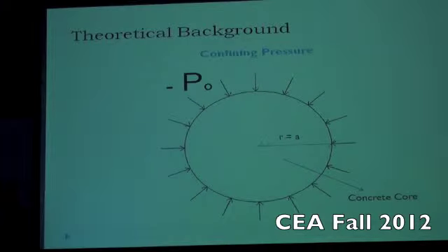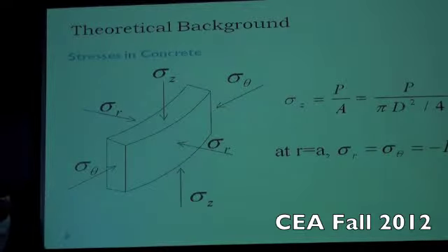Here in this diagram, P naught is the reaction when the concrete core expands. It applies pressure on the confining tube, and then the reaction of this pressure is P naught, or negative P naught in this case, because in our case P naught is the pressure applied by the edge of the concrete core on the plastic tube. And we denote a as the radius of the concrete core. Okay, these are the stresses in the concrete.